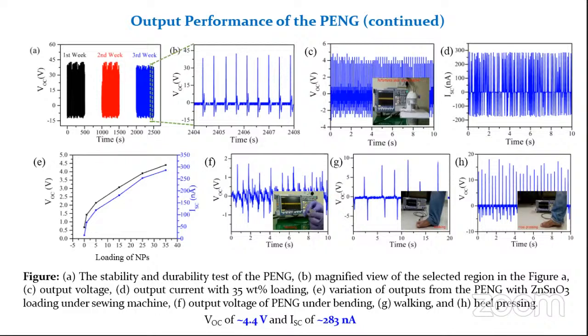Also, the fabricated PENG is very much capable of harvesting energy from the sewing machine. So you can see here, under sewing machine tapping, we have got 4.4 volt of open circuit voltage and 283 nanoampere of current. This is very much less because the probe of the sewing machine is very small. When the probe is applying pressure, the region is very small. That's why we are getting less voltage and current. And our fabricated device is also able to harvest energy from several biomechanical motions like bending, heel pressing, and walking.